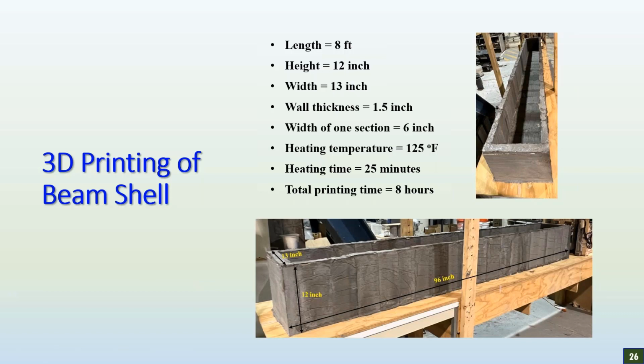So moving towards the 3D printing of first beam shell elements, we developed a 3D printer which can do 3D printing of beam shells. In the beginning, a beam shell was used with a height of 12 inches and width of 13 inches. The wall thickness was kept as 1.5 inches, and each section of 6 inches was printed in one segment, and it was heated up to 125 Fahrenheit. To move the printer, the heating time was given as 25 minutes. So it took a total of 8 hours of printing time to 3D print an 8 feet long beam specimen, which is shown here. This is the final specimen, which was 3D printed using the section printer developed at FIU.